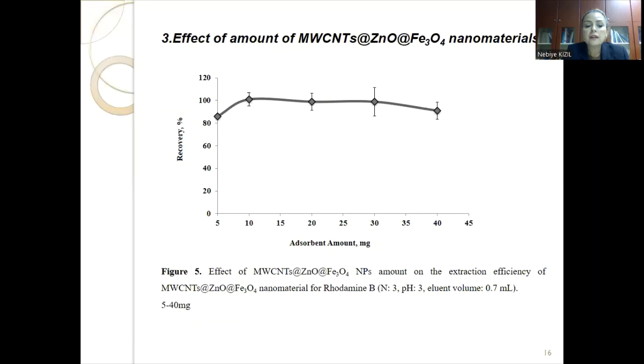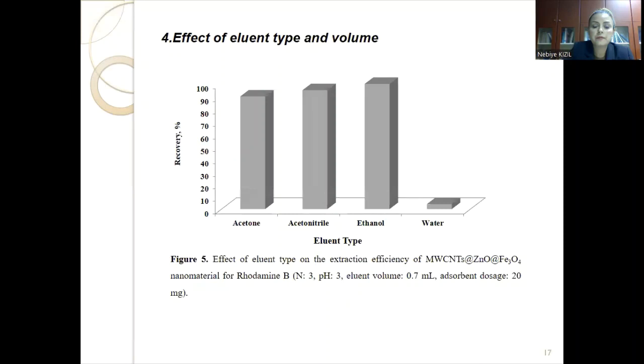Now we investigated the effect of amount of nanomaterials by adding in the range of 5 to 40 milligram to the model solutions. Maximum extraction efficiency was obtained with 10 milligram. Eluent type: many solvents like acetone, acetonitrile, ethanol, and water were used. Quantitative recovery results were obtained with acetonitrile, ethanol, and acetone. Maximum recovery values were reached with ethanol, 0.7 milliliter we used.